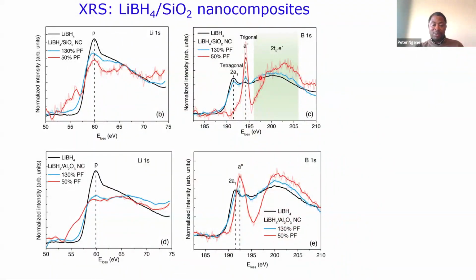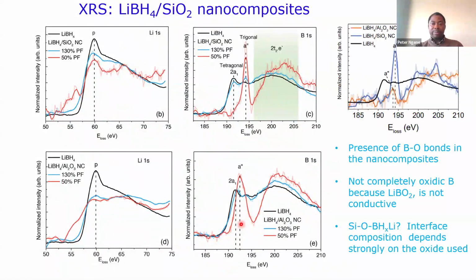So this is the same loading as this one, yet the peak shift is actually different from the one that is confined in silica, which means that what we can conclude from comparing the silica-based scaffold and the alumina-based scaffold is that the interaction at the interface is slightly different, because we can see, even for this, that there are two contributions at a point. So this is what we can conclude from this.